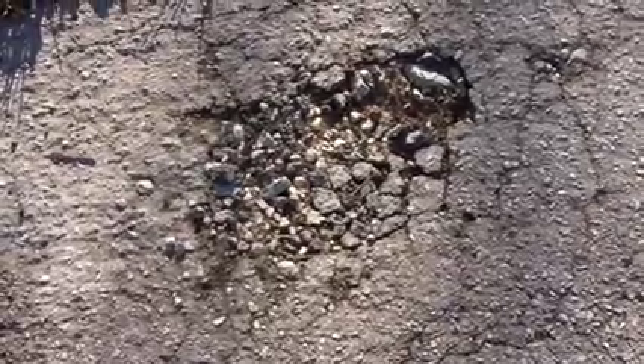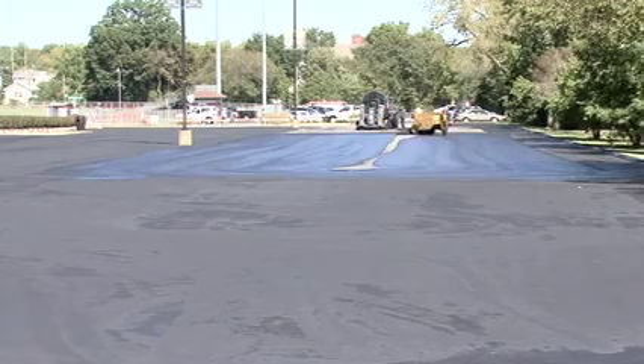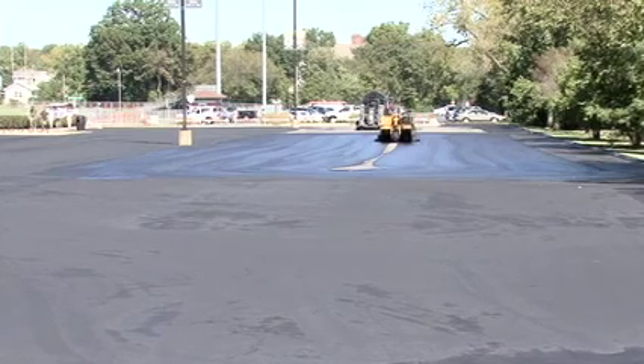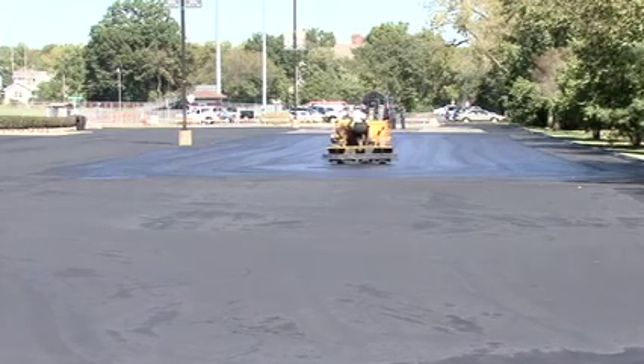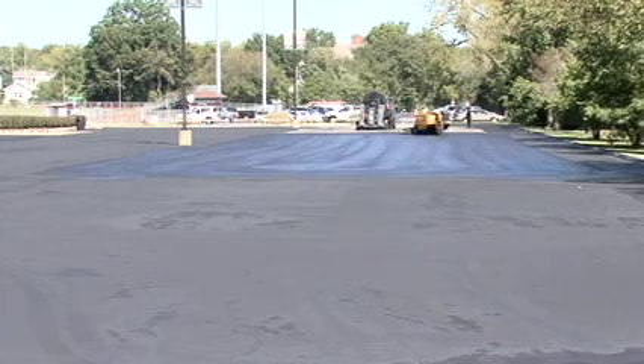So the goal of seal coating, whether it be a parking lot or a residential driveway, is to keep that asphalt binder in place and keep the water from penetrating the asphalt to get to the subbase and causing movement, cracks, potholes, things along those lines. So when I talk to a customer, I let them know that you've invested $10,000 in the driveway, or $200,000 into this commercial parking lot. After generally 1 to 2 years, it's time to start maintenance on it.